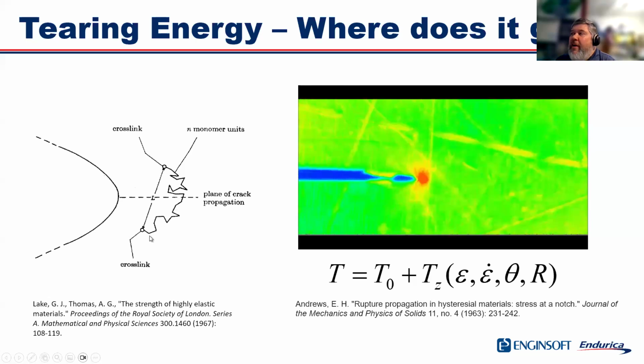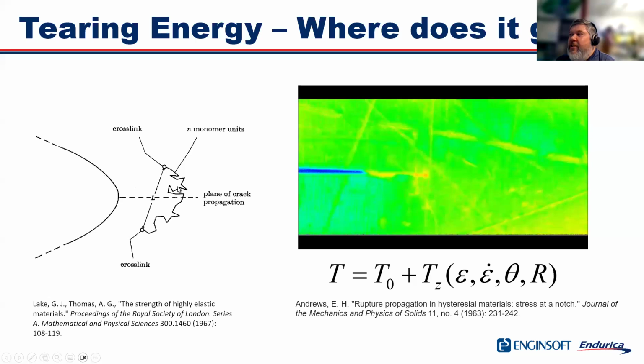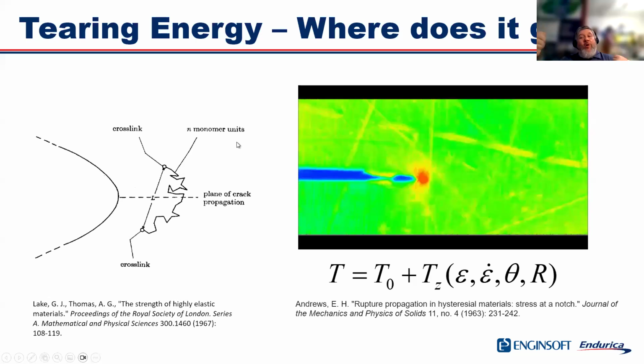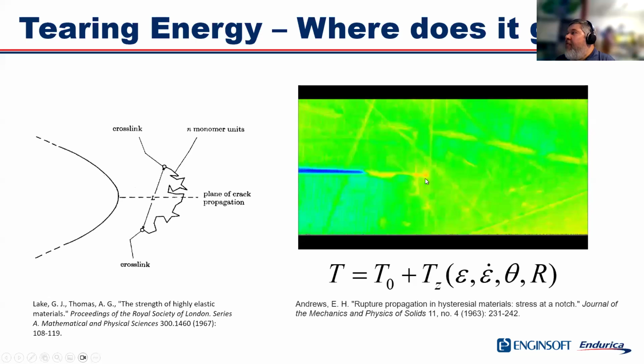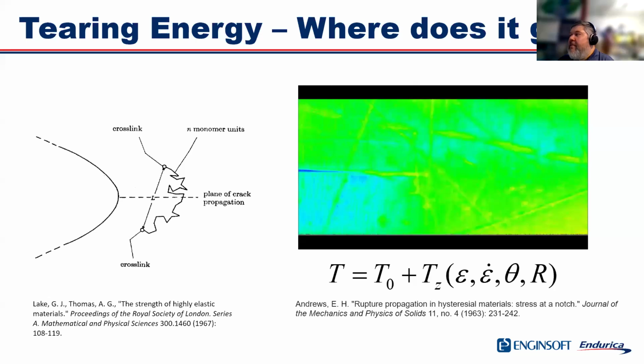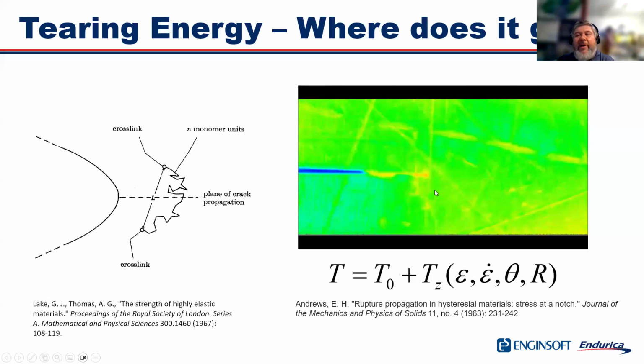Now, it turns out that's part of the energy that you need, but in order to get this polymer chain to load up to its breaking point, you have to stretch all the neighboring chains almost to break. And in the process of doing that, you're going to create viscoelastic dissipation. So in front of the crack tip, before the polymer chains break, there is this region here. This is an animation of an actual crack growth test. It's been imaged with an infrared camera, so you can visualize the temperature field in front of the crack. And what I want to point out is this red spot, right? There's this region in front of the crack where you have a large amount of heat generation, or mechanical energy being converted to heat. That's what we call the crack tip process zone. And of course, that takes energy as well.